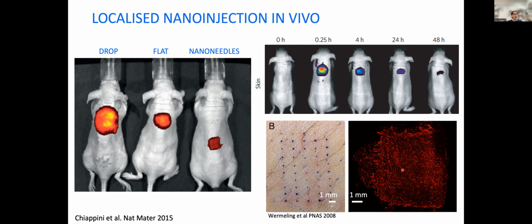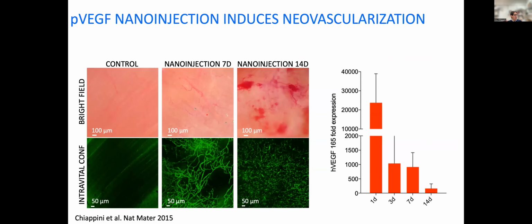Instead, when you deliver with nanoneedles, you see that you have a much more uniform distribution of your payload throughout the area of the tissue that is interfaced. And indeed, when we did this to the muscle of an animal, and we delivered the plasmid coding for the vascular endothelial growth factor, which stimulates the generation of new vasculature, we could see that over the course of 2 weeks, the animal did grow new vasculature that was attached to the original vasculature of the animal. And this new vasculature growth was driven by the expression of the gene that we had inserted. This was just a proof of principle that we could actually do that.